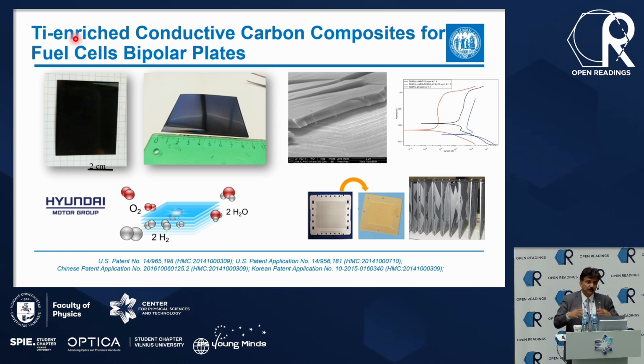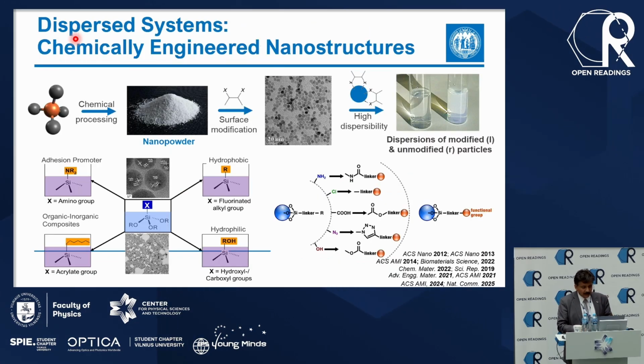So one idea was to give a highly conductive carbon matrix. And we know graphene is interesting because it has a very high conductivity in the plane. So if you can make a very metal-rich carbon matrix, this is what we did here. And the other approach to the same is using powders. Right? You do the powders.